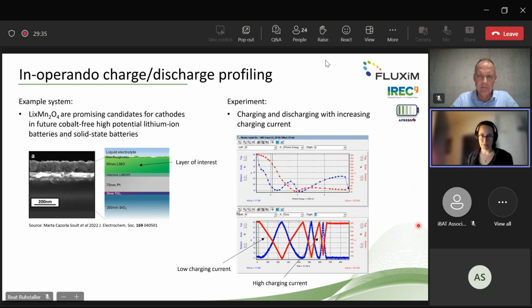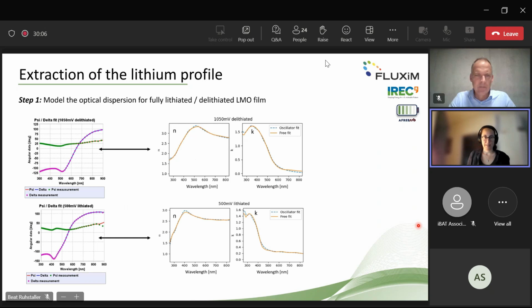And then they measured. Here on the right-hand side, you can see a screenshot of their software. They apply the different charging and discharging currents, change the time, and measure in situ. Here at the top, you can see the spectroscopic ellipsometry functions, psi and delta. And here at the bottom, you can see one point in energy as a function of time, as they charge and discharge. This was basically the experimental data set.